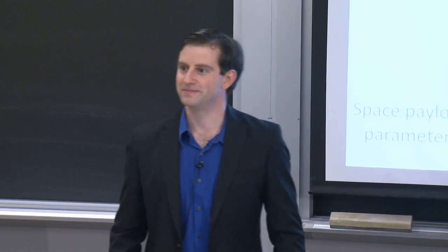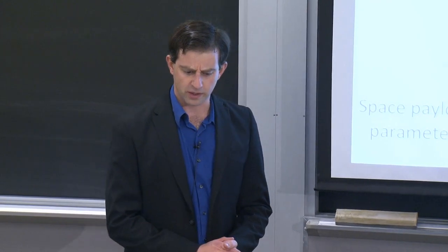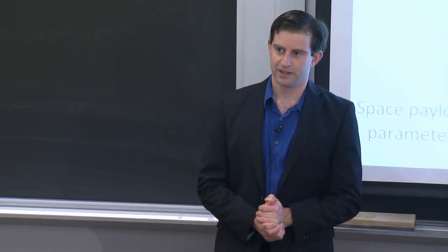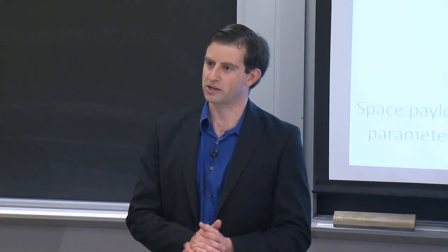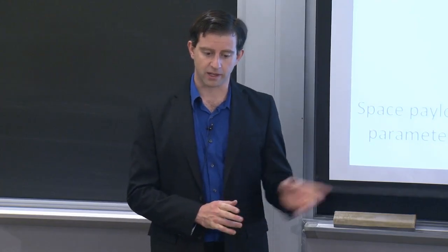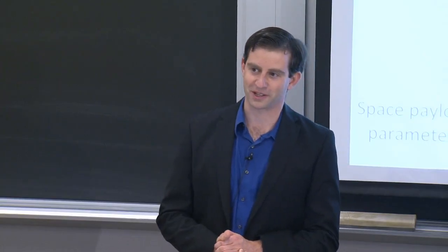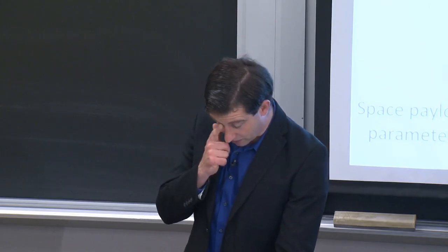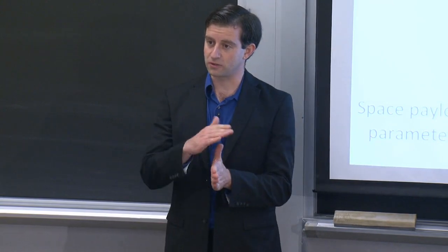Question? Do you know why the Cadmium telluride improves? Oh, why does it improve with efficiency? I don't know specifically why that is for this particular case, but I do know that some materials are what are called defect tolerant. Some are more naturally able to withstand anti-site defects or a certain concentration of damage, internal surfaces, voids, grain boundaries. Cadmium telluride is fairly defect tolerant. It's one of nature's gifts to humanity in that regard. The degree to which a material can be defect tolerant depends partly on the carrier density. If you have very high carrier densities, you tend to screen defects.